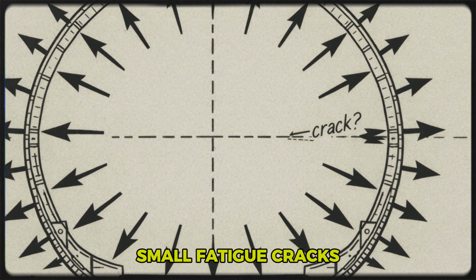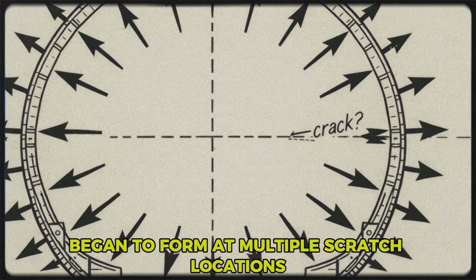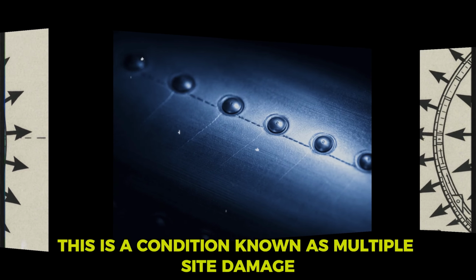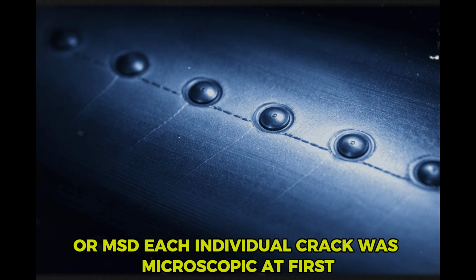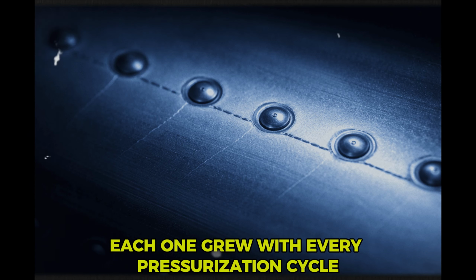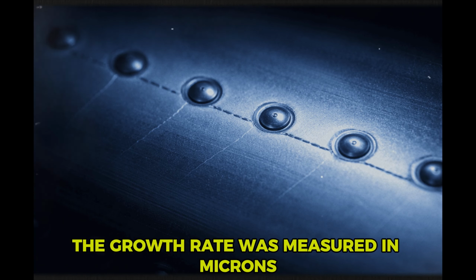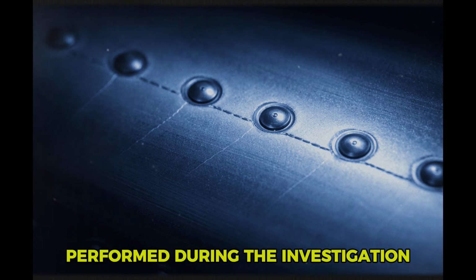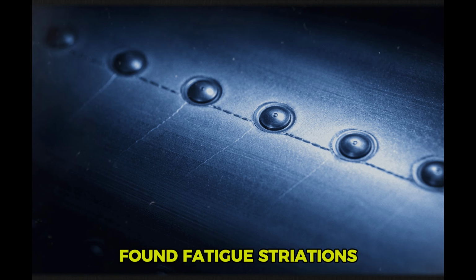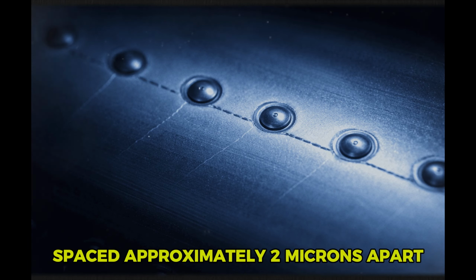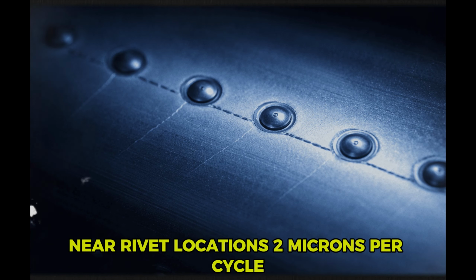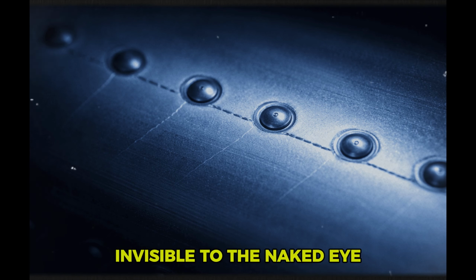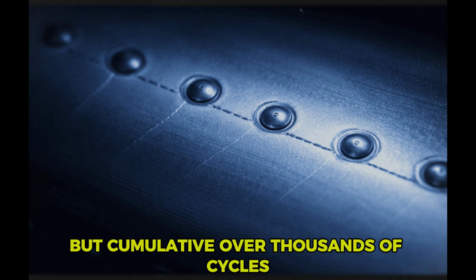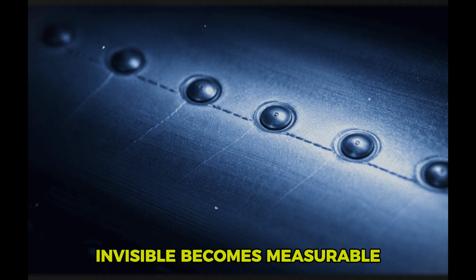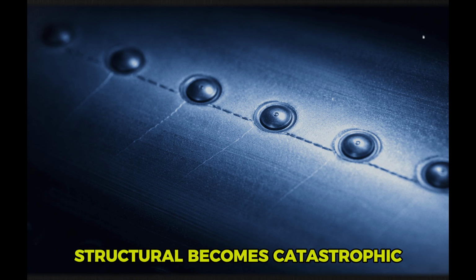Over time, small fatigue cracks began to form at multiple scratch locations. This is a condition known as multiple site damage, or MSD. Each individual crack was microscopic at first. Each one grew with every pressurization cycle. The growth rate was measured in microns. Scanning electron microscopy performed during the investigation found fatigue striations spaced approximately 2 microns apart near rivet locations. 2 microns per cycle, invisible to the naked eye, but cumulative over thousands of cycles. Invisible becomes measurable, measurable becomes structural, structural becomes catastrophic.